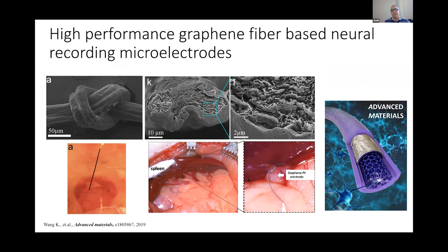Electrodes for recording are mostly based on metals, which are rigid and don't have high surface area. People try to modify them by coating them with high surface area conducting materials, but there are some issues, for example, delamination. In one of the meetings that I had with Gordon, we said, instead of coating a soft material on a rigid material, what if we do the opposite, so we get a soft, high surface area material, and coat that with a highly conducting metal, which was platinum, can we solve that problem? So we did that. With graphene, we could have high surface area, and with platinum coating, we could have high charge collection because platinum is a good conductor.